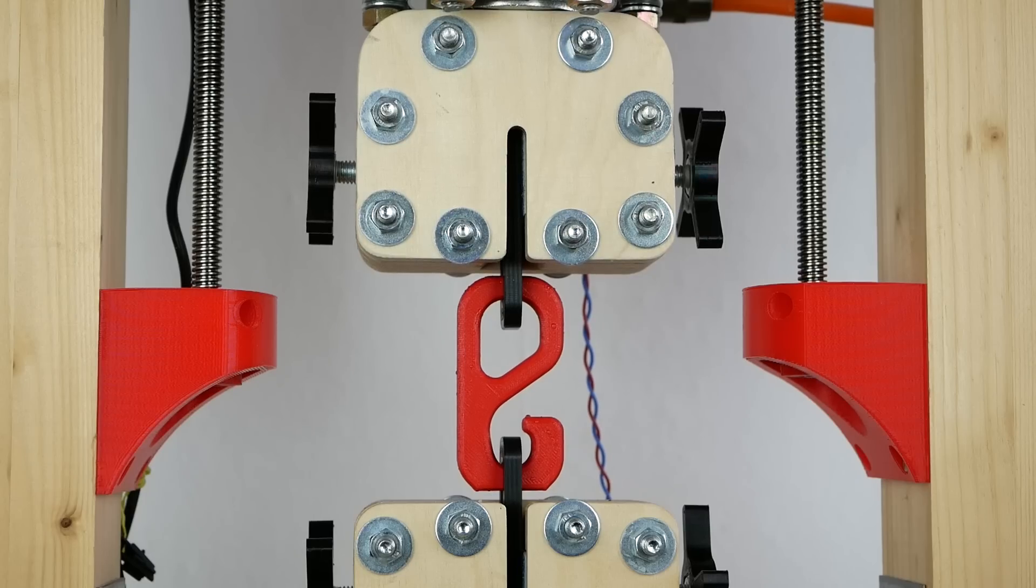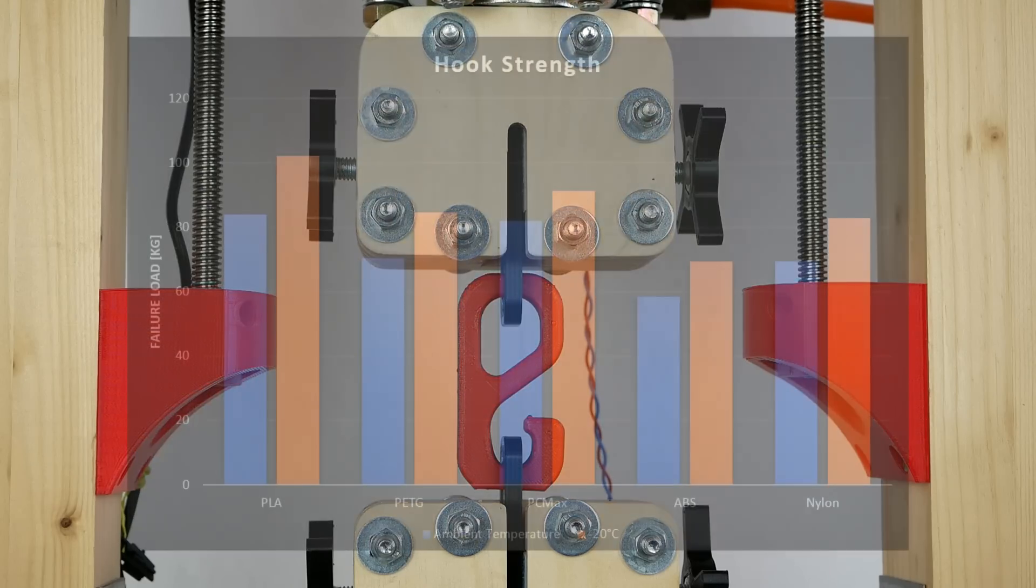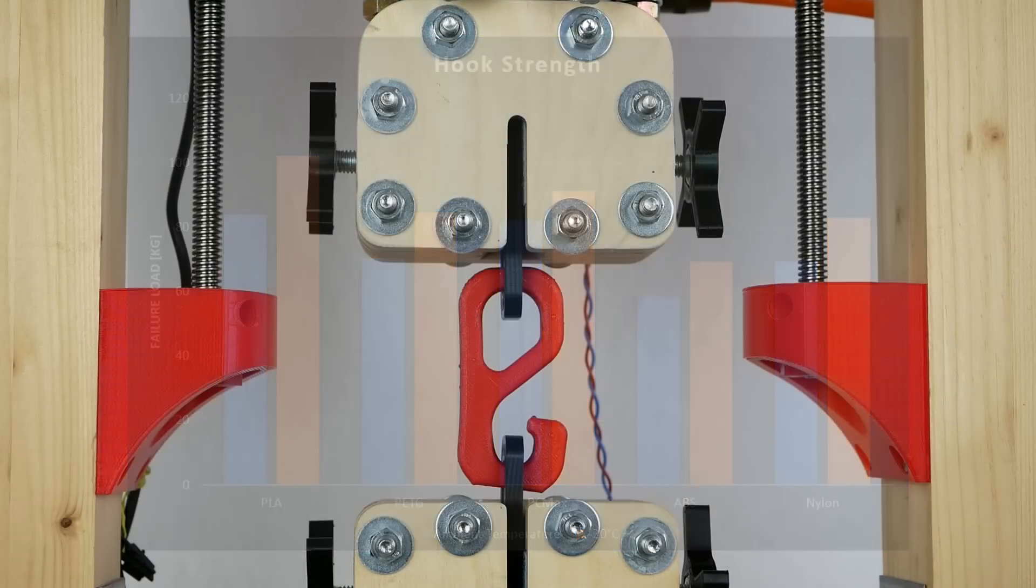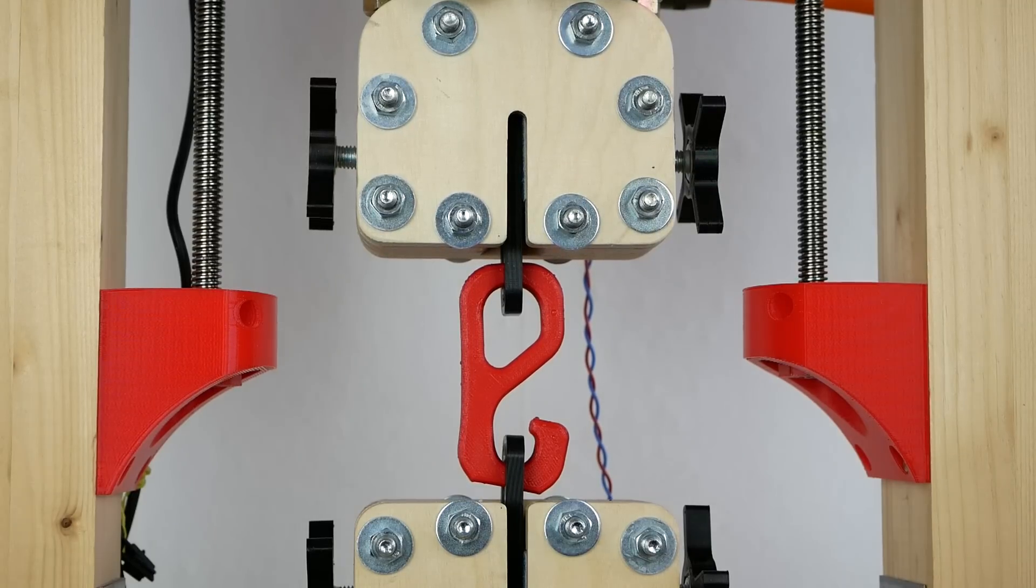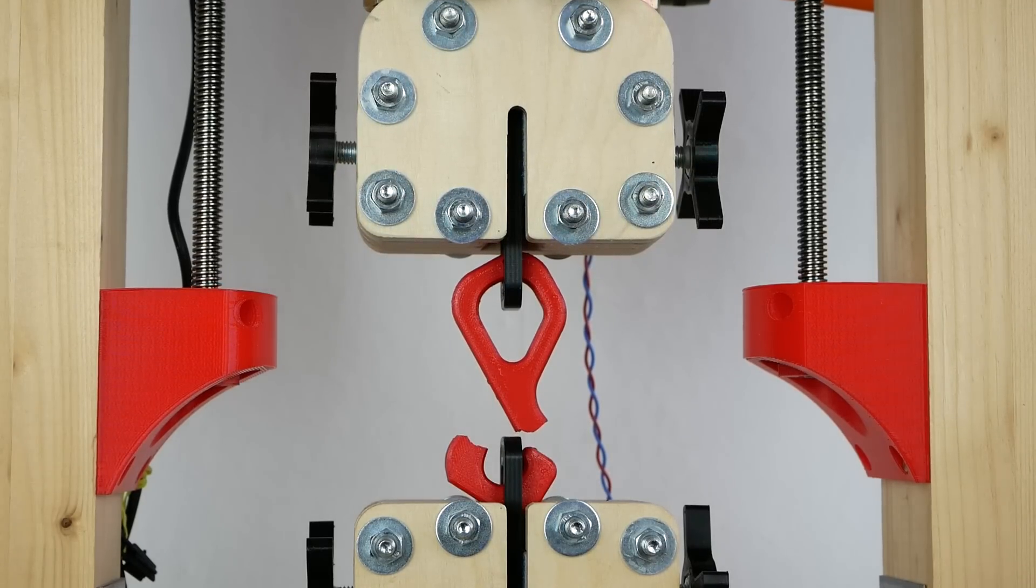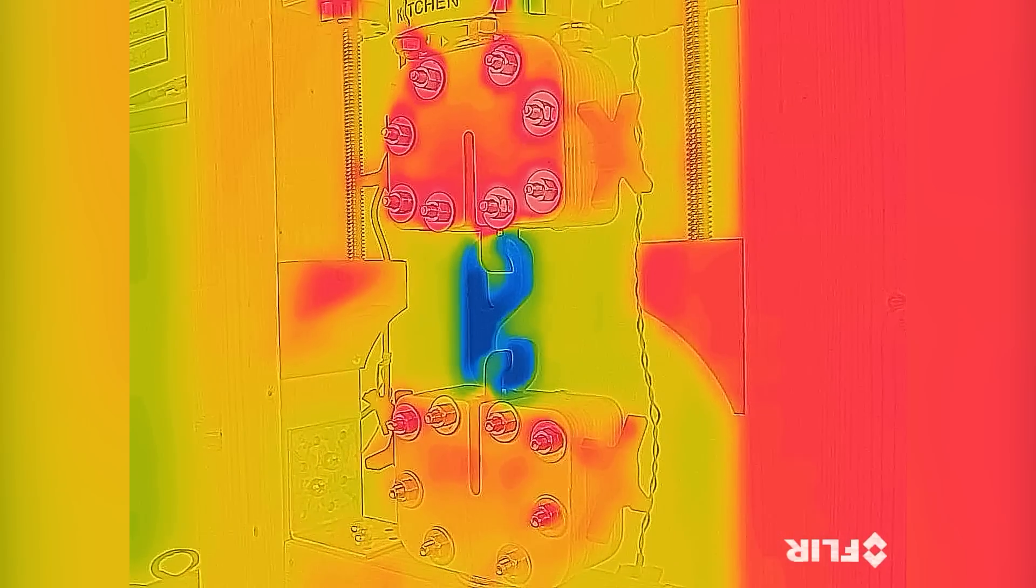The result of the hook tests surprised me quite a bit in the beginning because all the hooks were able to bear more load at minus 20 degrees Celsius than at ambient temperature. It took over 100 kilograms to get the PLA hook to fail. Polycarbonate improved from 82 to 91 kilograms, PETG from 71 to 85 kilograms, nylon from 79 to 83 kilograms and also ABS improved by almost 20% to over 80 kilograms of failure load.